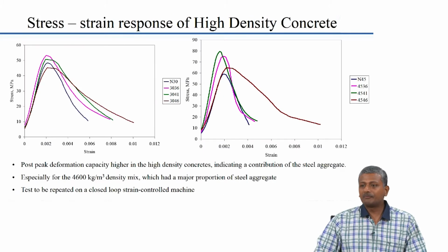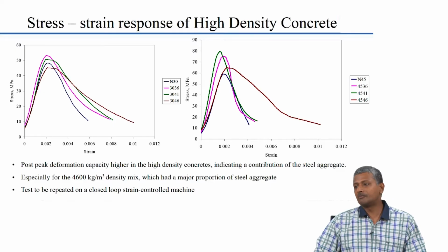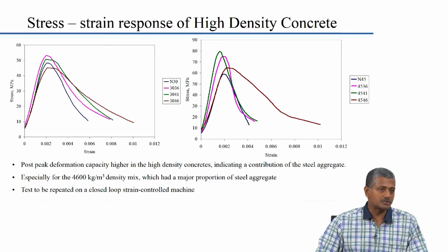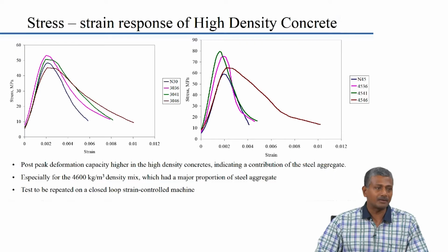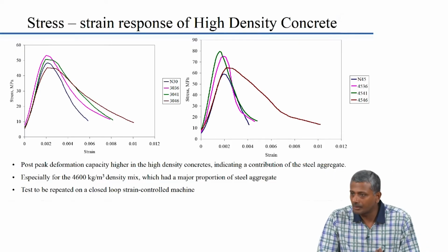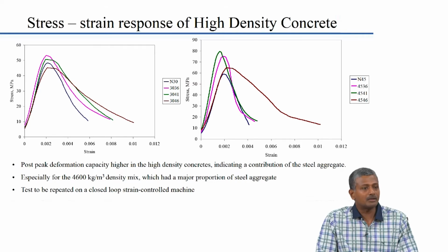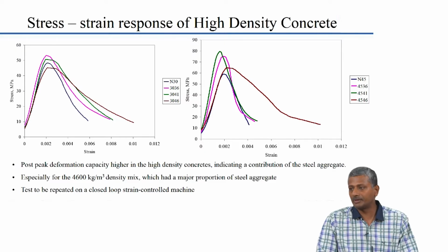Now, this is another example that we had actually done in the lab when we wanted to study the stress strain characteristics of high density concrete. Now, high density concrete typically is used for very specific applications like the radiation shielding in nuclear reactors, for instance. There you need densities typically in excess of 3.5 gram per cubic centimeter, and generally this high density is obtained by using heavyweight aggregate. Instead of using normal limestone or granite based aggregate which have a density of close to 2.8, 2.9, we try to use hematite or magnetite or ilmenite aggregate where densities are typically more than 4.5 or 5. Okay. So, when you use these aggregates, obviously the resultant density of the concrete is also very high.